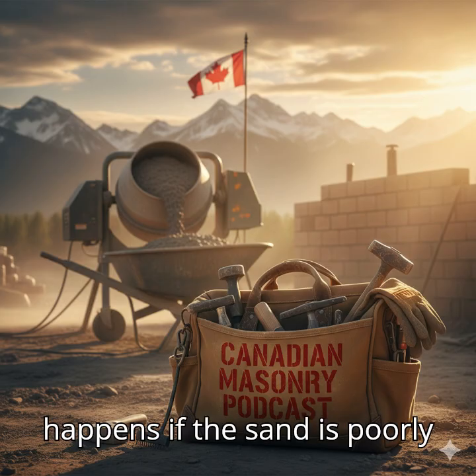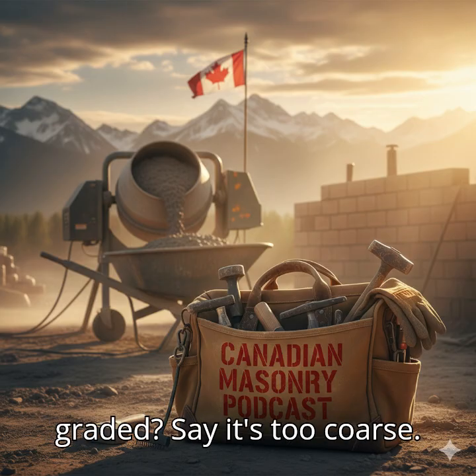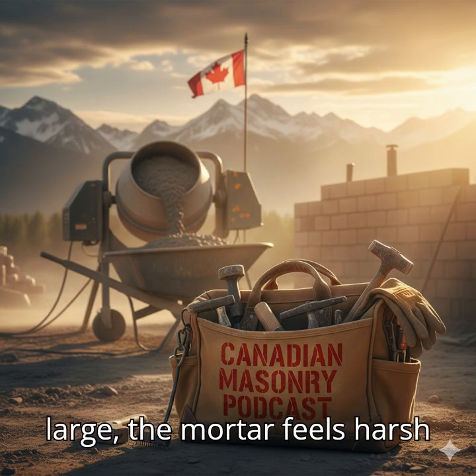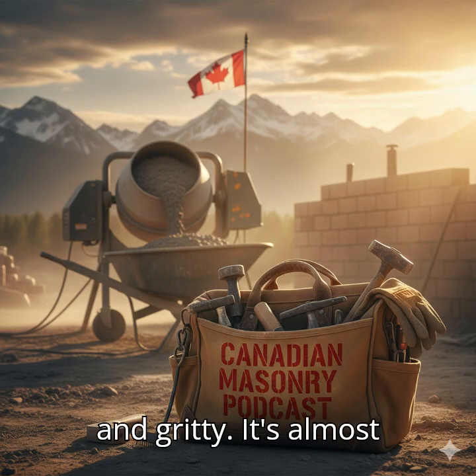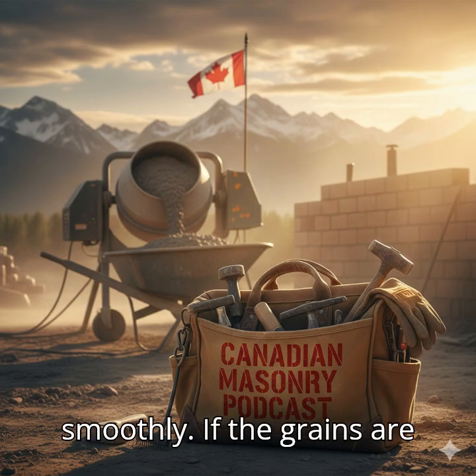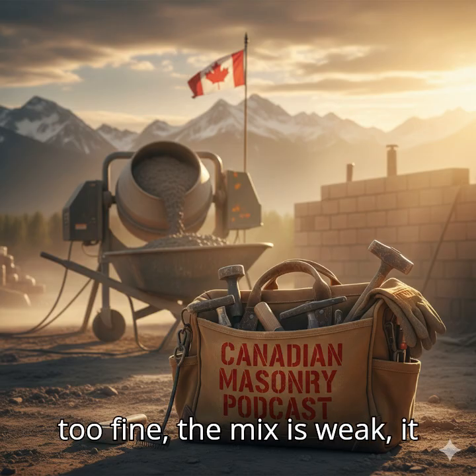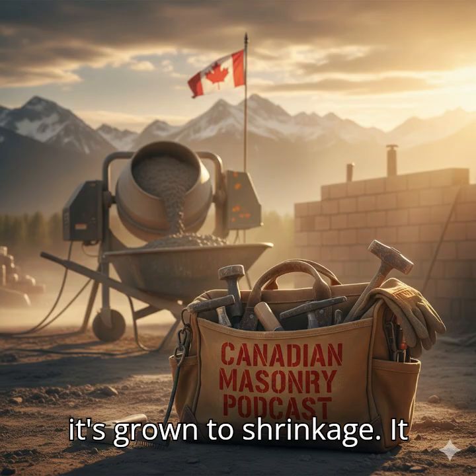What happens if the sand is poorly graded? Say it's too coarse. If the sand grains are too large, the mortar feels harsh and gritty. It's almost impossible to spread smoothly. If the grains are too fine, the mix is weak, it needs too much water, and it's prone to shrinkage,